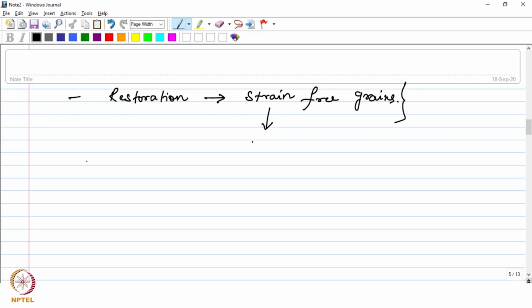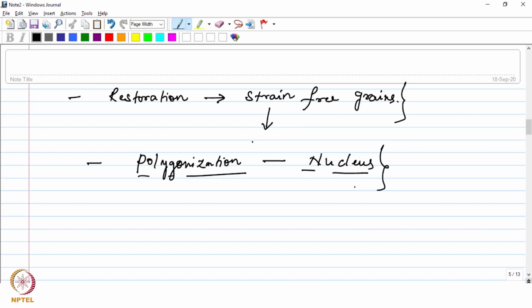For example, one of the mechanisms says it is through polygonization. Because it is a recrystallization process, right? You have to form the new strain-free grains. So you need a nucleus first, which will be free of any strain, and then as that nucleus reaches a critical size, it is going to grow and consume the strained grains. And that is how the strain-free grains will form all over the material, and it will be recrystallized, right? So one mechanism says that the nucleus forms through the polygonization process that we discussed in the previous class, right?